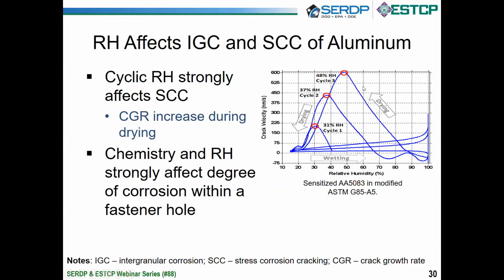The point that I want to make here is, when you cycle these things backwards, you can see that once you're in this, again, subdeliquescence region where we see exfoliation, where we see corrosion still occurring, you get large increases in the crack growth rate. And in this example here, these increases in growth rate become more severe the longer you run the test. I'll note that also these things are a strong function of the solution chemistry, so pH and what you do. So if you were to run this in a G85A5 versus an A2, you get significant differences in behavior.